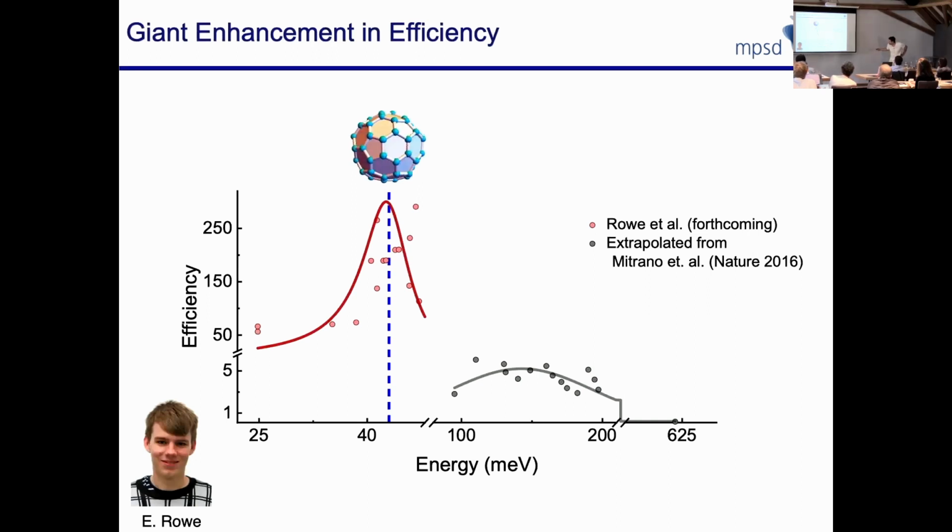So this was the Mitrano experiment, which at the time we thought was something really very satisfying. However you fit this, the scatter has to do with the fact that with the powders, every time you measure them, you make mistakes by a factor of 2 in the way you couple pump and probe into them. But pretty consistently, the efficiency, as measured in some way that I can detail if you're interested, becomes between 50 and 100 times more if you pump at 50 meV. And when you pump here, there is no penetration depth mismatch between the pump and the probe, so the data comes out of the lock-in and it's just very reliable data. The reflection coefficient becomes 1. And so it's a lot more certain than before.